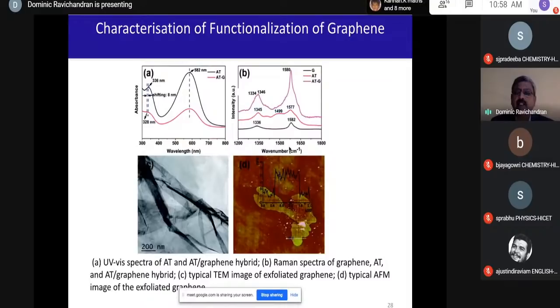When we go on to the Raman spectrum, the graphene has two bands, that is 1582, called your G band, which is specific for graphene, and the D band, which is for the deviations where you have some disturbance in the graphene, which is going to be at the D band of 1336. And you also see that the composites have additional peaks in the Raman spectrum.